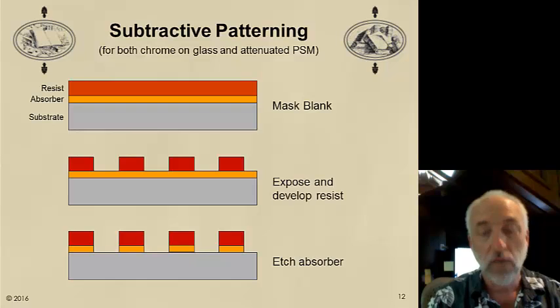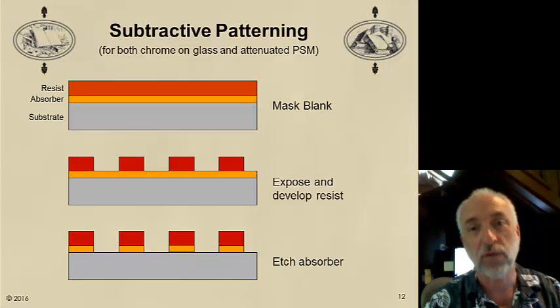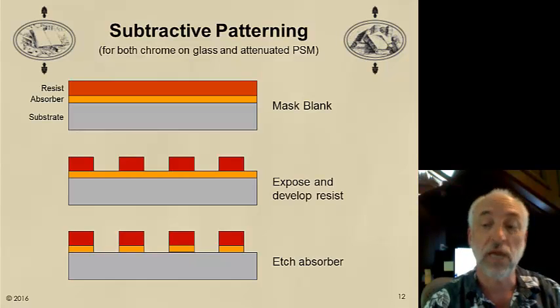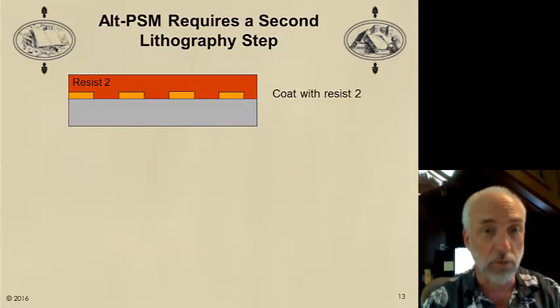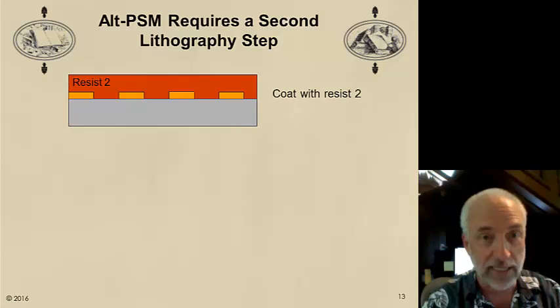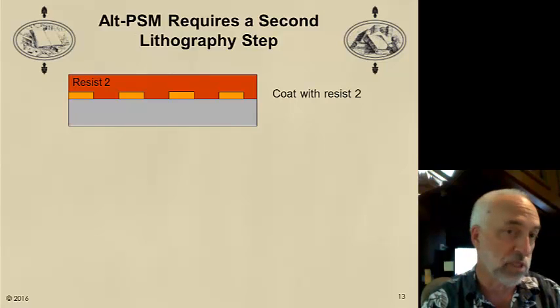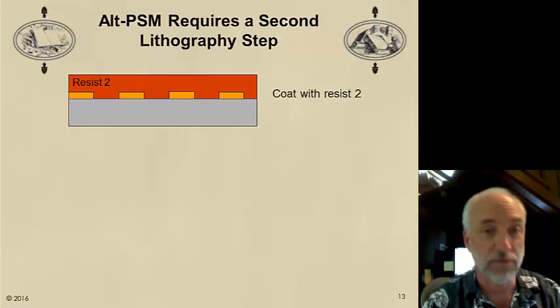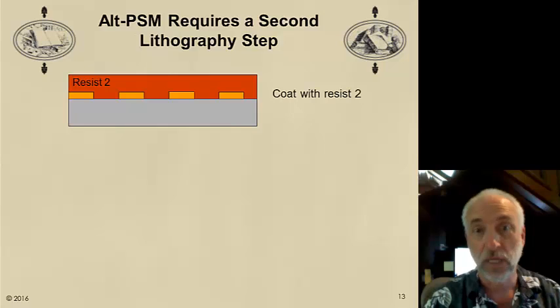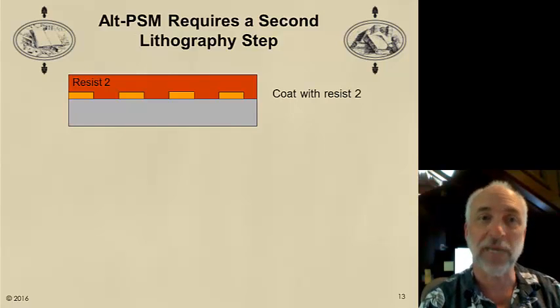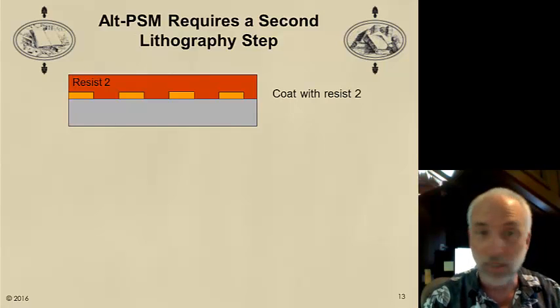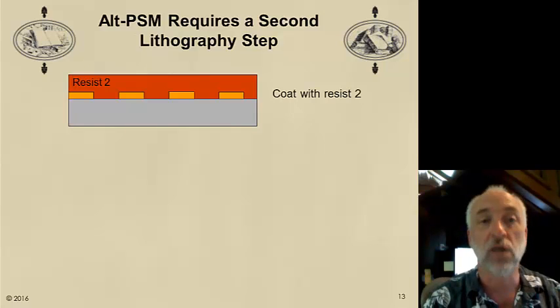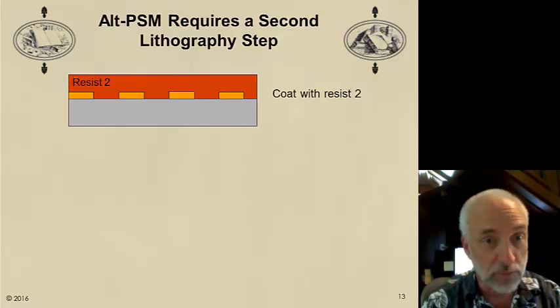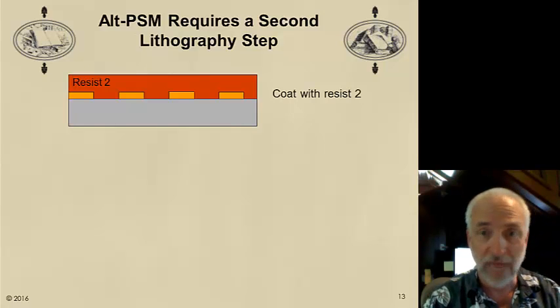We have a mask. But with an alternating phase shifting mask process, we have another set of steps to go through. In fact, we have another lithography process to perform. We must coat the mask with a second photoresist material. We're coating over the topography of the absorber that we've already patterned in the previous step. So this is something new, right? In the conventional mask making process, we'll often buy the blank with the resist already coated on it. So many mask shops would never have to coat photoresist on their substrates. Well, here, if you're going to use an alternating phase shifting mask process, you must be able to coat photoresist, bake it, have it ready for exposure.